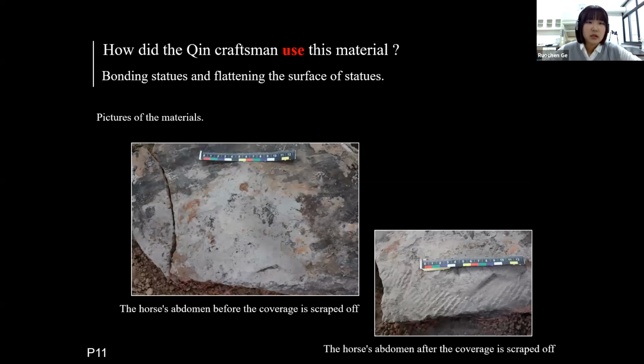The other possible intended use is flattening. We found a large area of a horse's abdomen is covered with this material, making this area very flat. Regular impressions were found when the material was scraped off from the surface of the horse's abdomen, and they may be left by the supporting structure during the clay joining. Considering no trace of early fracture in this area, we think that this material was not used as a binder here, but to cover the rough surface to form a smoother surface. The material was initially semi-flowing and can be easily applied and polished.